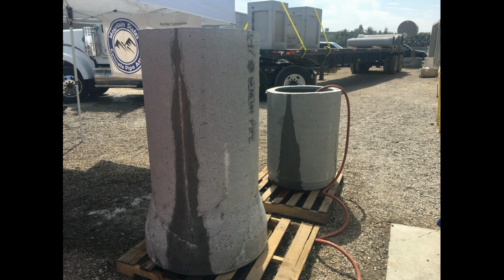We also filled the shorter one over there. We filled that with water and compared how fast the water was coming out of that one. If you're wondering, after 3 weeks, same pipe, same crack, just cut in half. After 3 weeks, we compared the water flowing out of it. The one that was closest to us was flowing out at a rate of about 1 inch of water per 2 hours. We did a 2-hour plant tour and it had gone down about 1 inch. So we still lost about 1 inch of water in 2 hours after 3 weeks.